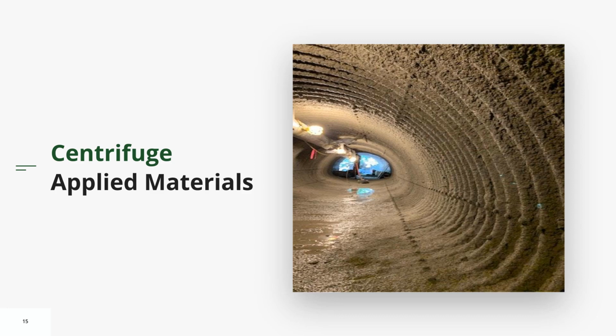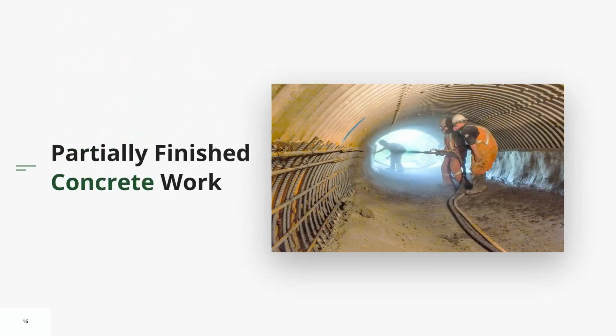Here's a more conventional case. This is when the pipe has failed, generally down at the 8 and 4 or even 9 and 3. So what we're doing is bonding to an existing pipe, making a composite product. The bottom becomes a concrete pipe, a continuous concrete pipe without joints, bonded to the steel. Then the steel on the obvert, or the roof if you want, of the pipe, being in perfect condition, is reutilized to continue to provide service for a further 70 or 80 years. This is a key part of rehabilitation. We're using the parts of the existing structure that are still in good shape, and augmenting that existing structure by building a new section to replace the part that has failed.